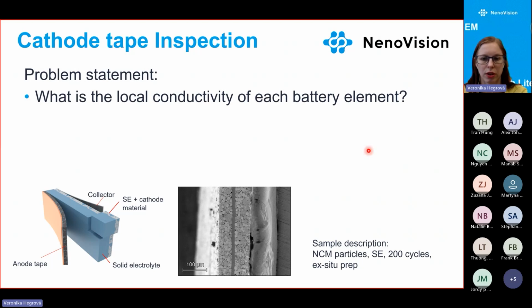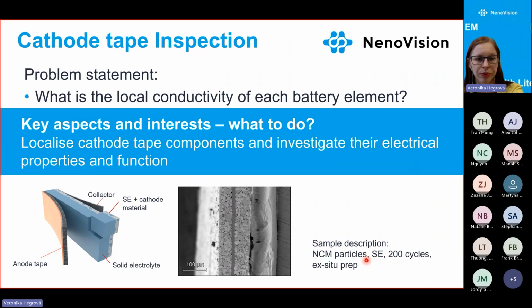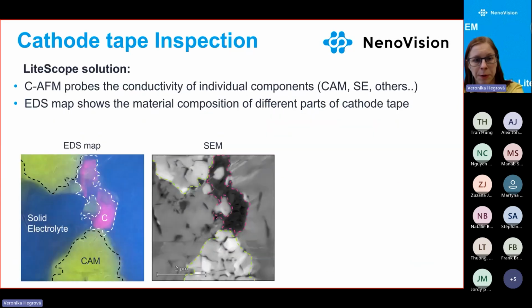What we're going to have a look at is a sample of nickel, cobalt, manganese particles in solid electrolyte. It was cycled 200 times and prepared ex situ. So we need to localize the components and investigate their electrical properties and function. First of all, we use the EDS to find what is the cathode material, what is the solid electrolyte, and where the carbon is.